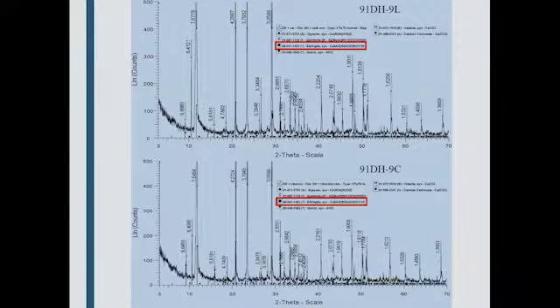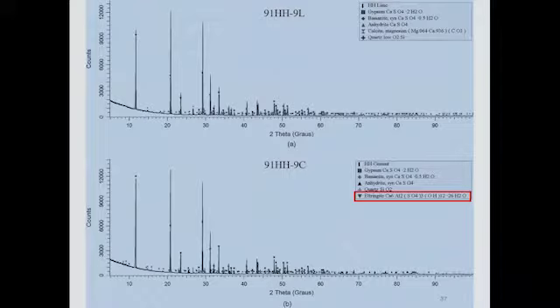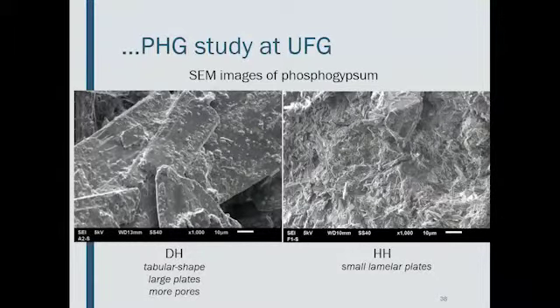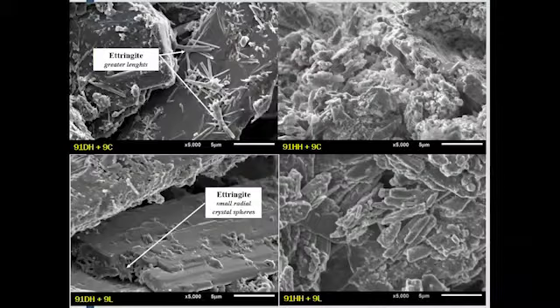By the X-ray tests, we observed that in the DH mixtures, we still have ettringite, which we don't want. But when we use the hemihydrate type, we observe ettringite only in the cement mixture. For lime, we didn't note it. And when we look at the images from the microscope, we observed first that the shape of the dihydrate type is different from the shape of the hemihydrate type. Here we have tabular, large plates, and because of this it is more porous. And here we have small lamellar plates, less porous, which can impact good behavior because of this microstructure.